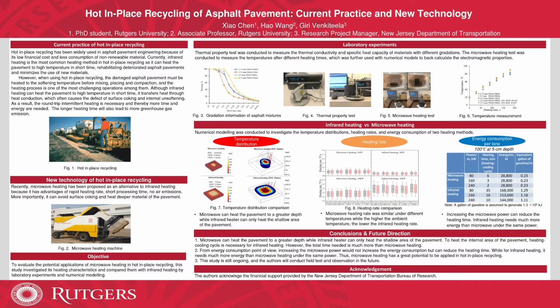But the microwave can heat the asphalt pavement to a greater depth, while the infrared heating can only heat the pavement to a maximum depth of about 3 centimeters under the power of 5 kilowatts. And also, the temperature gradient along the vertical direction in microwave heating is much smaller than the infrared heating. And from the heating rate point of view, in general, different asphalt mixtures did not have remarkable difference in the heating rates in both microwave and infrared heating methods. But the microwave heating rate was comparable under different temperatures, while the infrared heating rate becomes lower under a higher temperature. So it means when we use infrared heating under a higher temperature, more time is needed than expected.